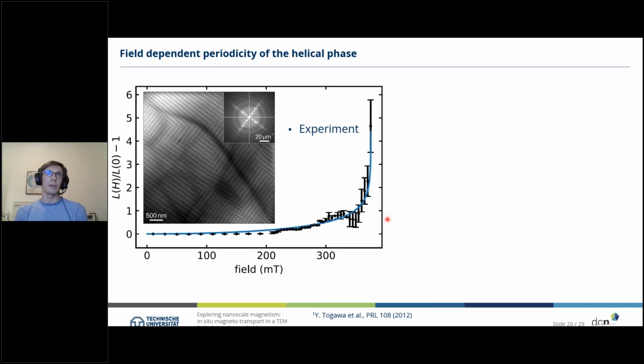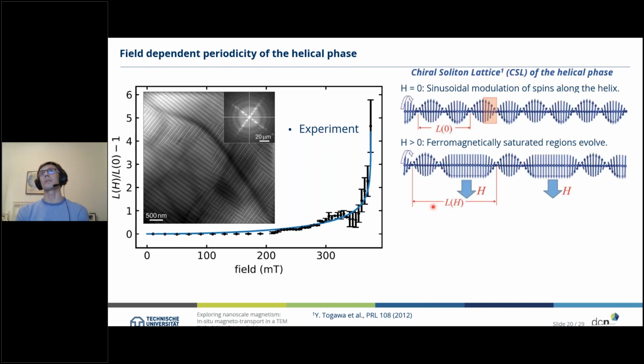And we can, of course, plot that as a function of the magnetic field, which is shown here in that graph. This is the normalized spacing as a function of the magnetic field. You see it's slowly increasing, and then at some point it's exponentially growing. That we can understand, if we dig a bit into the literature, by the so-called chiral-soliton lattice of the helical phase, starting in the ground state with a sinusoidal modulation of the spin structure in one direction, where you have a certain length.